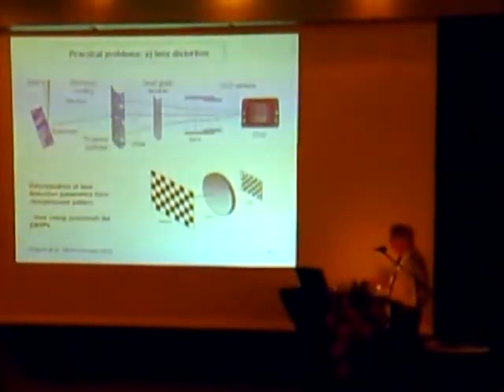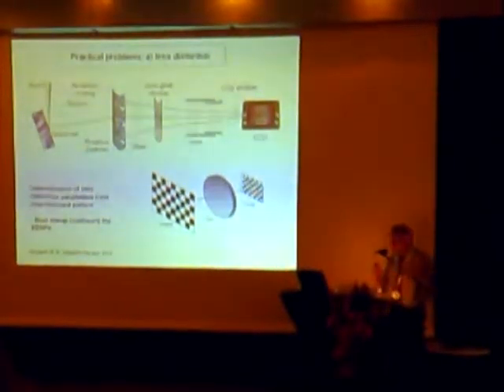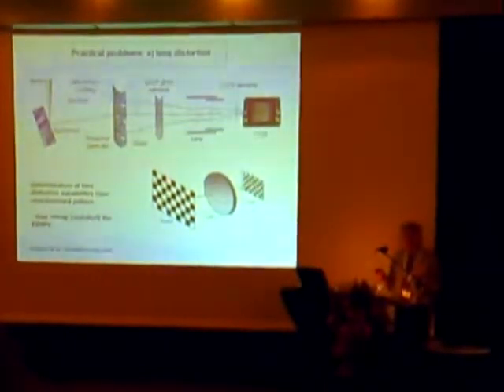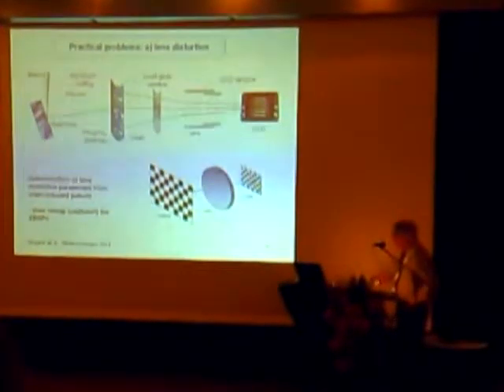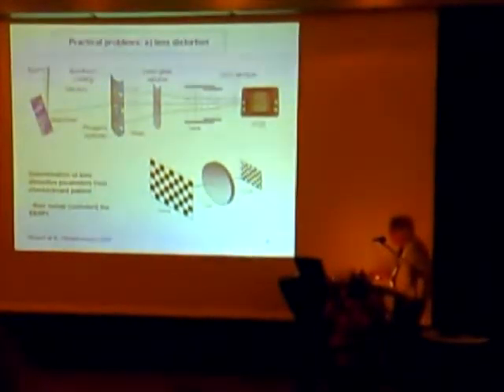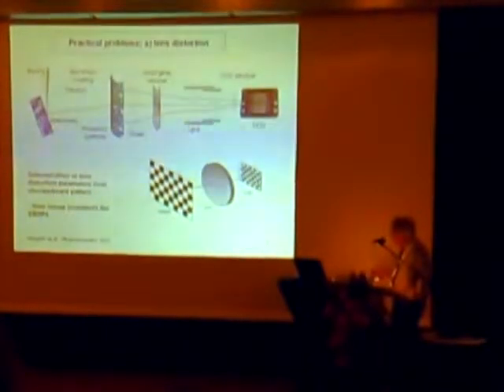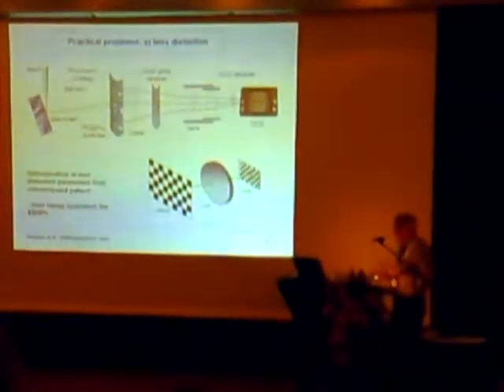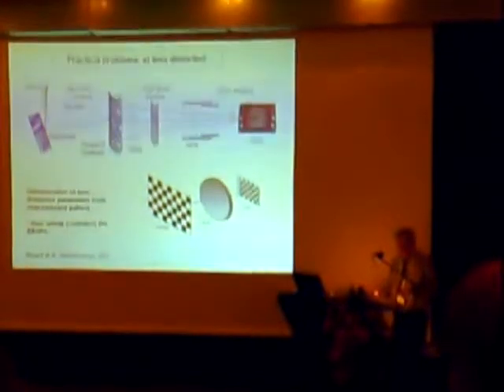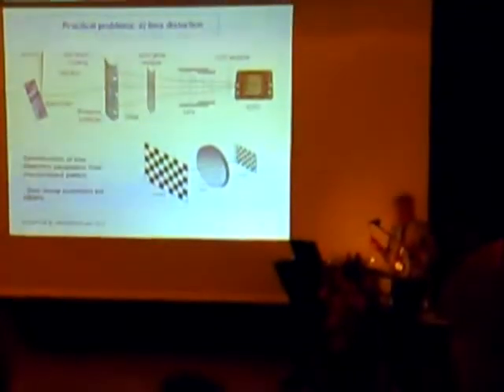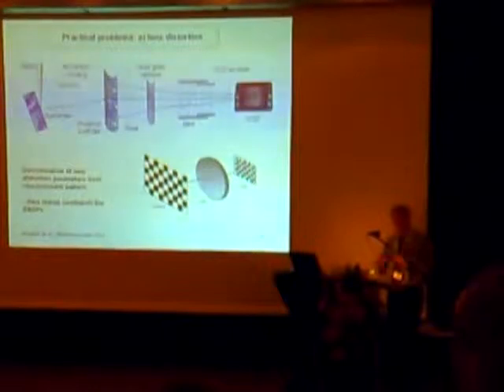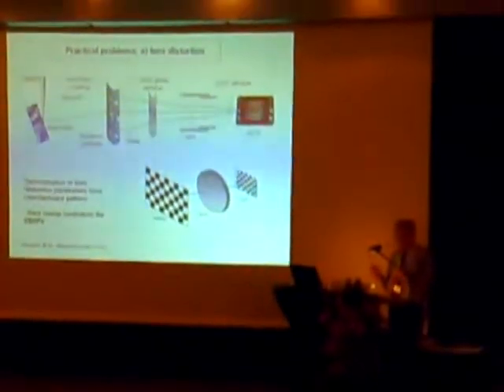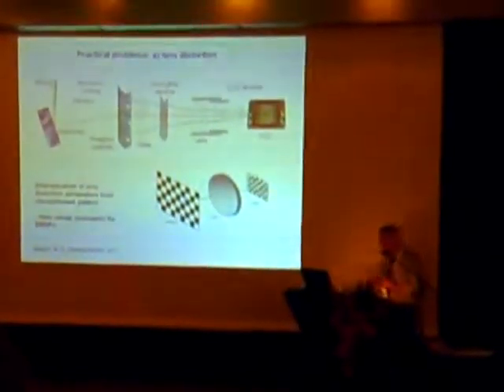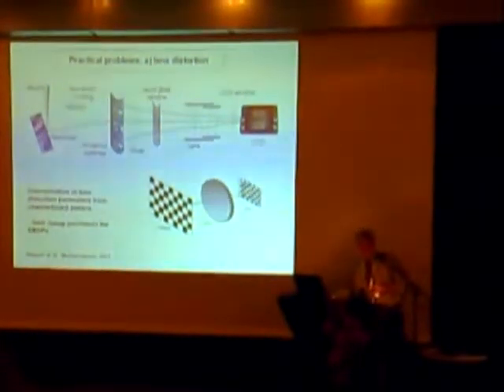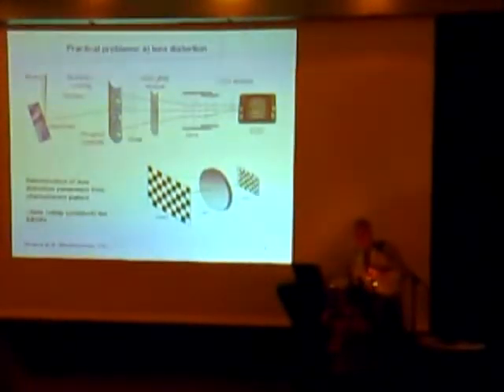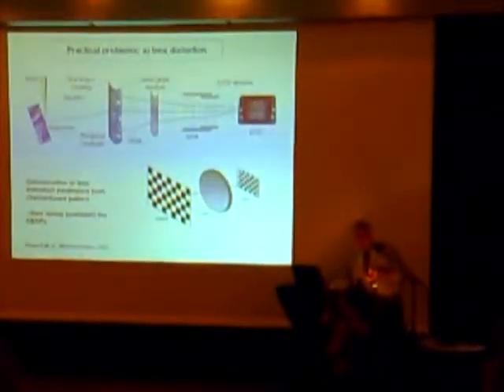You have to determine from this pattern the distortion parameters, and this is what has been done by image analysis people for 20 years. Right? You calculate the distortion parameters for your particular configuration, and then for each pixel, you remap or undistort the EBSD. So initially, you have to undistort your EBSD to correct for lens distortion. And in fact, to our knowledge, people have only started doing this about a few months ago.